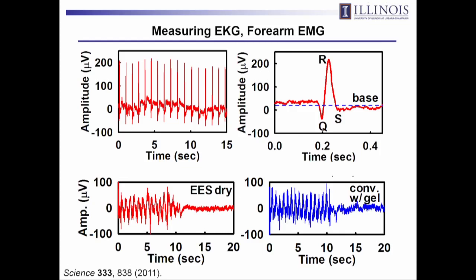As you can see, this overall envelope fluctuates. You can put these things on the leg. You can measure EMG, electromyography. That's electrical activity associated with the contraction of the skeletal muscles. So you can measure things about gait, as you're walking and then standing with this kind of epidermal electronic system. If you compare the signals to those that you capture with a conventional paste-on bulk electrode with a conductive gel, you see the signals are more or less the same.